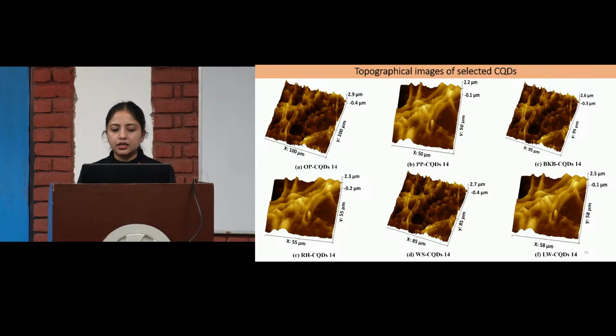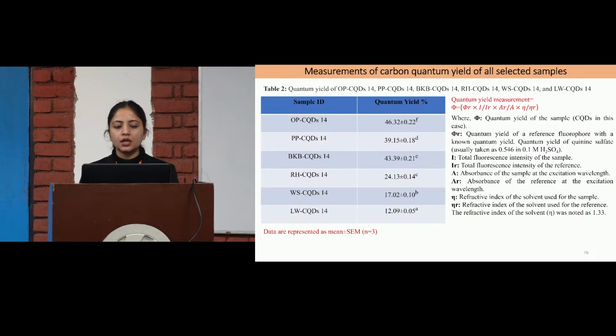So the height of one layer is 2.9 in the onion peel, 2.2 in the papaya peel. In the broken kidney bean, the height of one layer is 2.6. Then, for the measurement of the quantum yield of all the selected samples, we checked the quantum yield by applying the fluorescence intensity formula. So this is the formula, and we get the quantum yield of the selected samples. For the onion peel, the quantum yield was 46%, for the papaya peel 39, broken kidney bean 43, for the rice husk 24, and walnut shell 17, liquid whey.